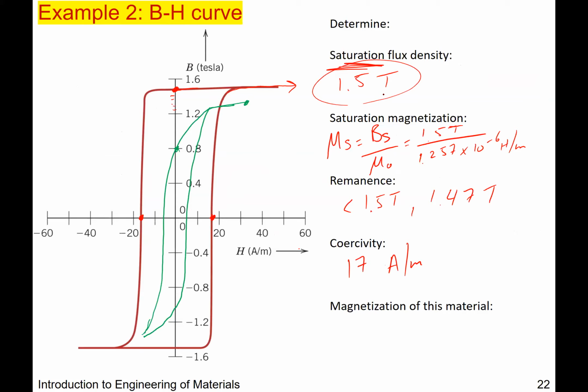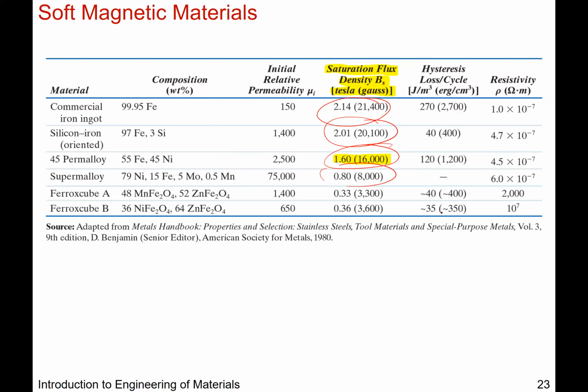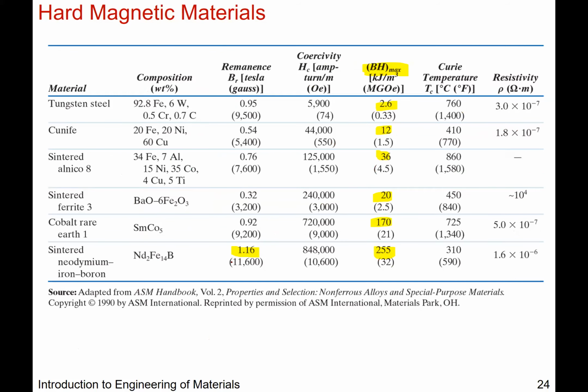So it could be a soft material, but then when we look at the remnants for hard materials here, we can see it could also be a hard magnetic material because the remnants is somewhat comparable to, let's say, sintered neodymium iron boron. So then what is it? Well, we can now look at a third parameter, the BH max. Here, that's the energy in quadrant 2. And this is on the order of kilojoules per meter cubed. So that's actually 2,600 joules per meter cubed.